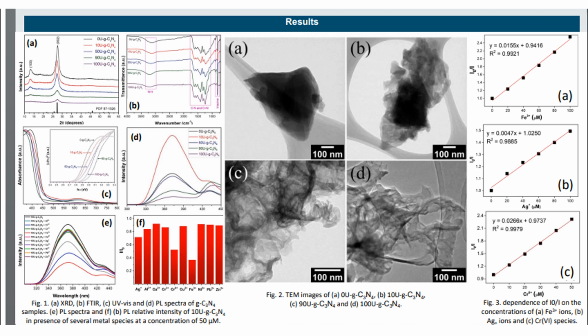The 10% urea sample was used for metal ion detection according to its higher luminescent properties, achieving limits of detection of 7.2, 8.4, and 1.9 micromolar for iron 3 ions, silver ions, and chromium 6 species, respectively. Notably, our graphitic carbon nitride is prepared by a simple, inexpensive method and does not require complex synthesis processes.